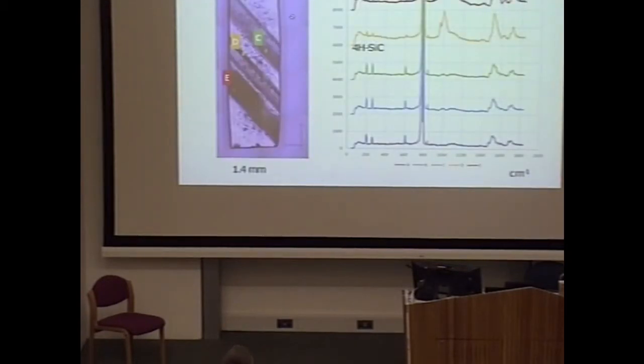This is a Raman spectra of the deformed silicon carbide. So A, B, C, D, E, these areas, we measure the Raman spectra. And against E, we can see this kind of spectrum. And these lines around 200 Kayser, this shows the 4H silicon carbide. But in the C, E region, there's no peaks around this area. This means that this area becomes the 3C silicon carbide.